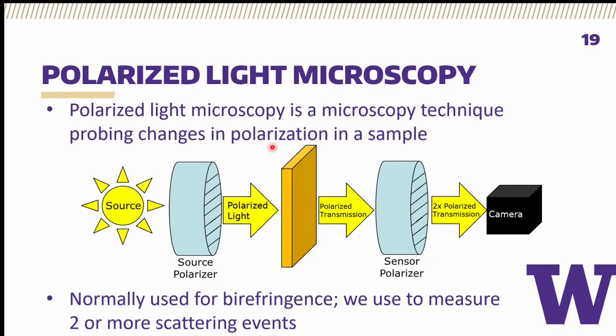To characterize this optical haze, so to speak, in the system, we use polarized light microscopy, a regular light microscopy technique with 2 polarizers on either side of your sample that have rotating axes relative to each other. For this technique, there are 2 measurements of interest. When source and sensor polarization vector lines are lined up, they are in parallel, and you get what approximates a normal light microscopy image, a bright field image. But when source and sensor polarizer are rotated 90 degrees relative to each other, you'd expect to see, based on elementary physics, just a completely black square.